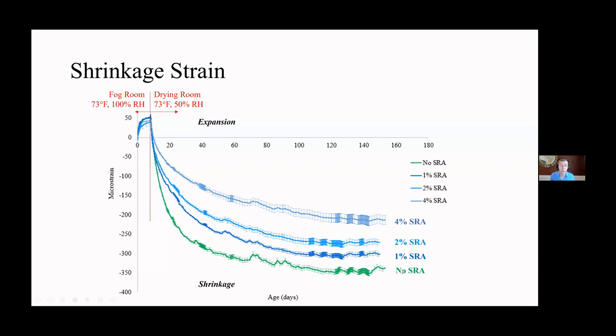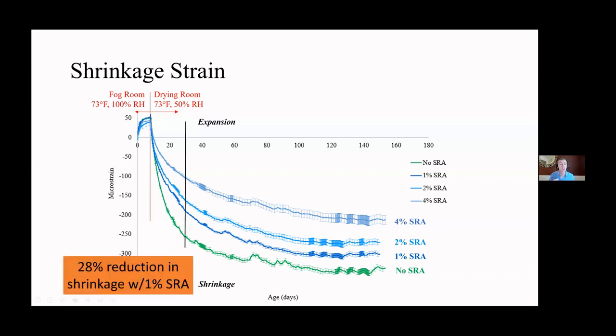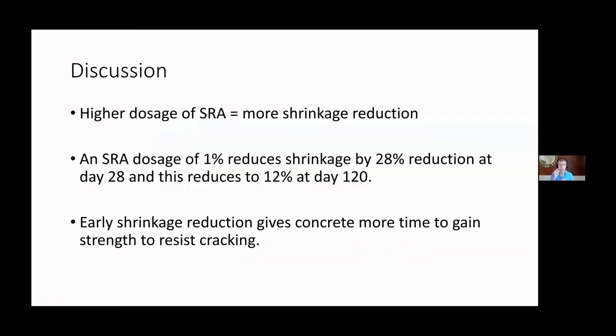But we're going to show that if you use around 1% SRA, you still get a lot of benefits. You get about 28% reduction in the shrinkage here at about 30 days. And this early age shrinkage is really important. Higher dosages of SRA do equal less shrinkage, but this 1% shows a lot of promise. It reduces our shrinkage by about 28% at about 28 days, and a little bit less at later days. But this early age shrinkage reduction is a big deal because it gives our concrete time to gain strength, and it doesn't have as much strain that it has to resist.